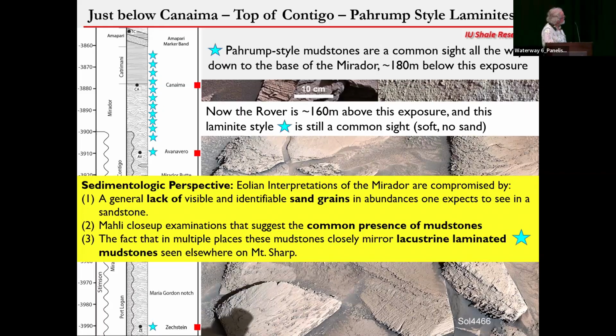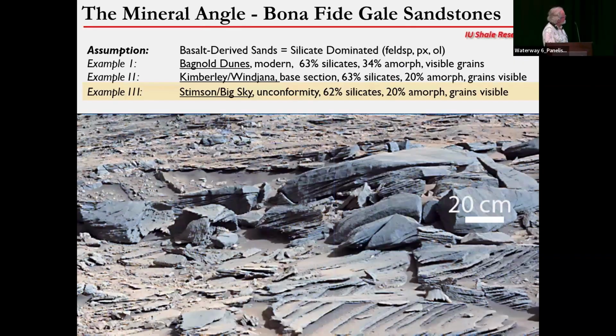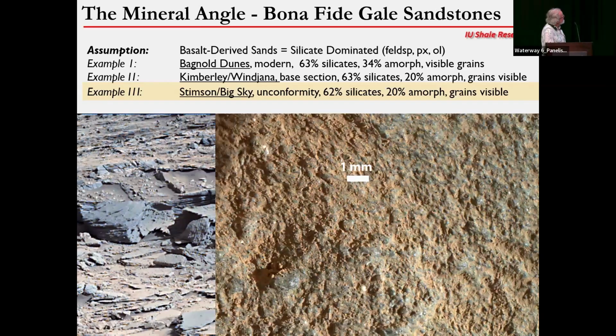So the sedimentological perspective is that an Aeolian interpretation of the Mirador is compromised by a general lack of visible and identifiable sand grains in abundances that we would expect to see in a sandstone. The second point is that the MAHLI close-up examination suggests a common presence of mudstones, and the fact that in multiple places these mudstones closely resemble lacustrine laminated mudstones that essentially everybody on the MSL team has agreed upon also works against this. And then we have also a perspective based on ChemMin data.